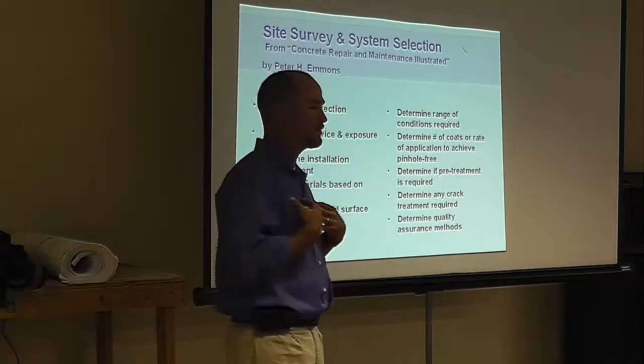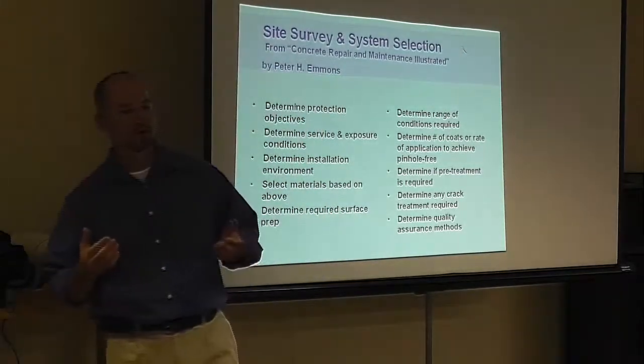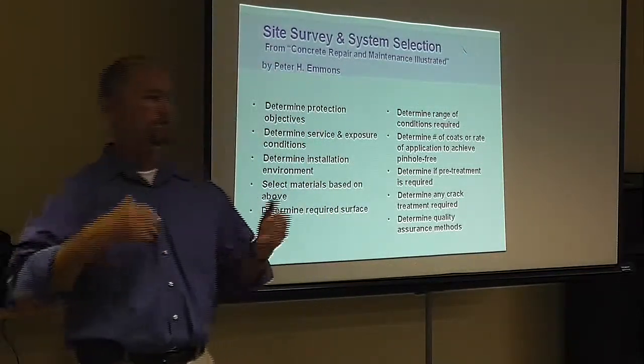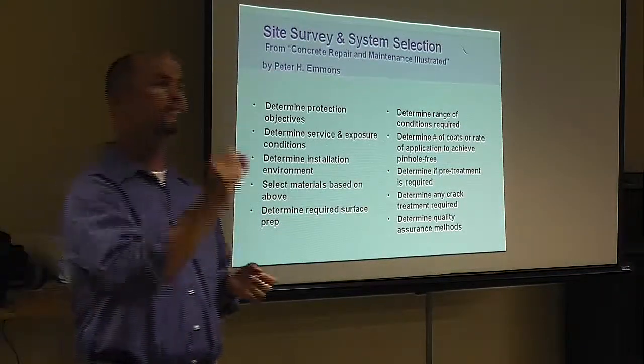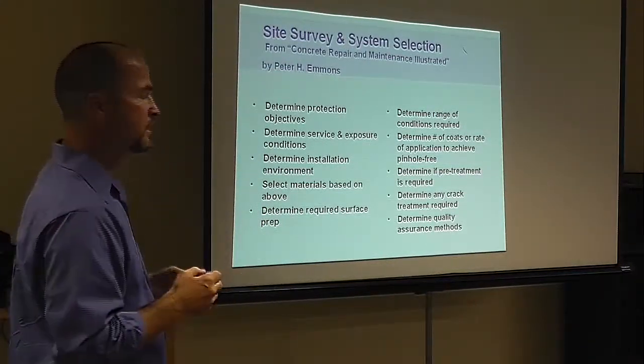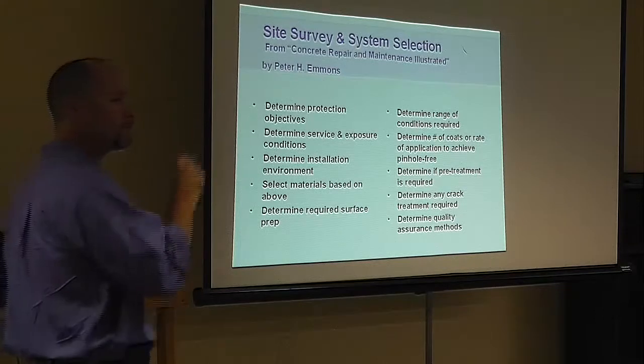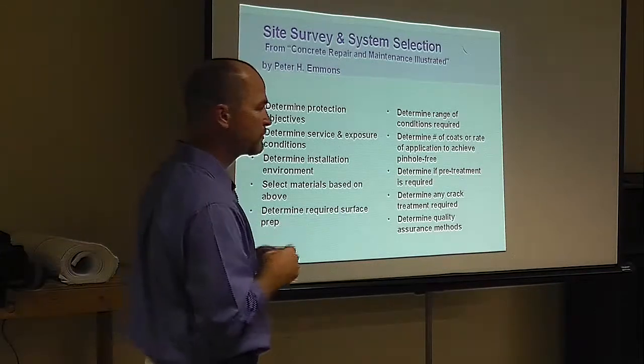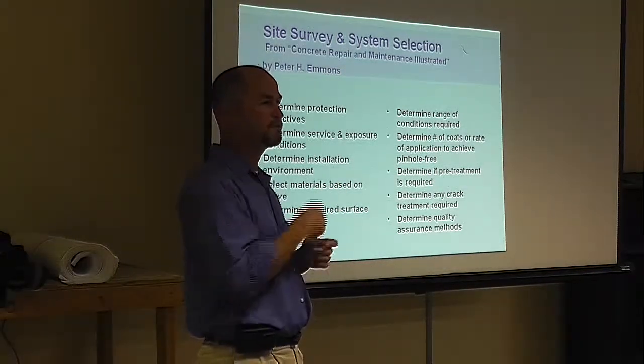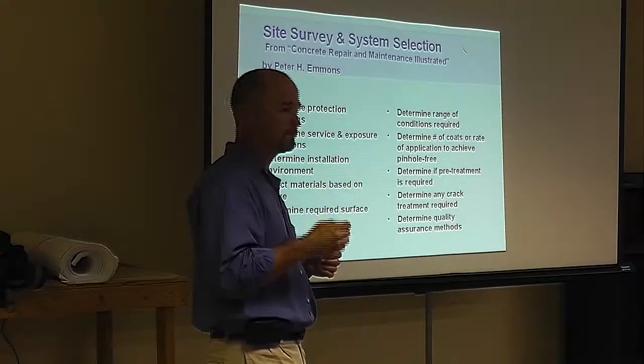I go to projects all the time and they say, well, we put 2 coats on there. Well, they put 2 coats on it at 400 square feet per gallon. It's very, very thin. That's not pinhole-free. Doesn't matter how many coats, it matters the total mil thickness of that coating. High build coatings would be about 14 to 16 mils. Paints are usually dried at about 4 or 5.